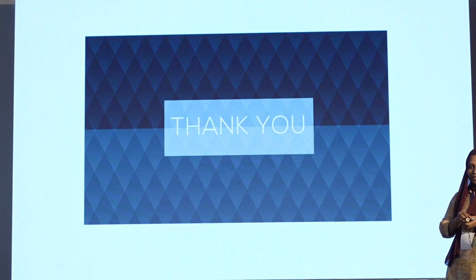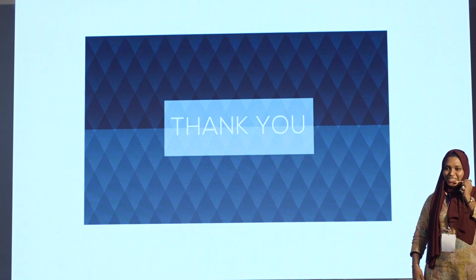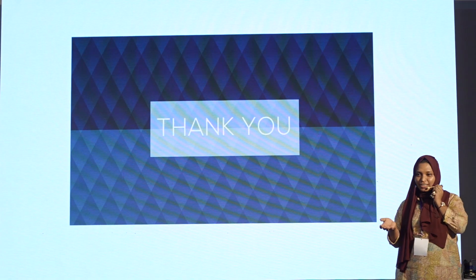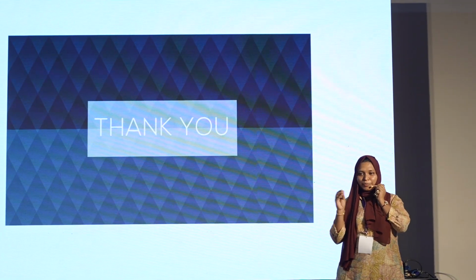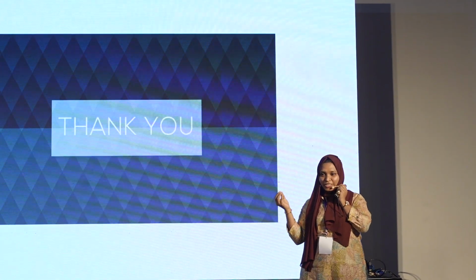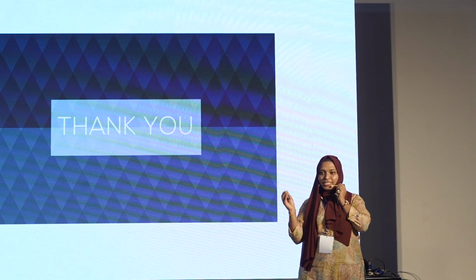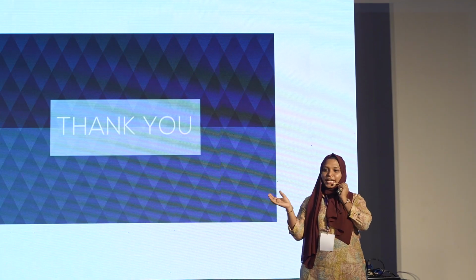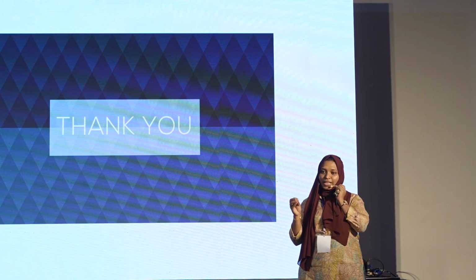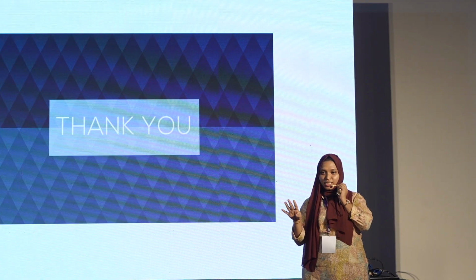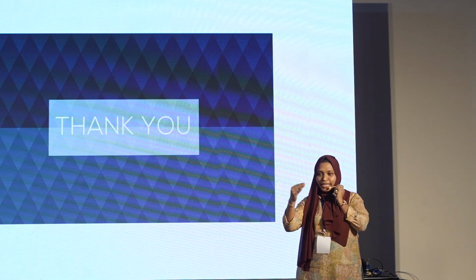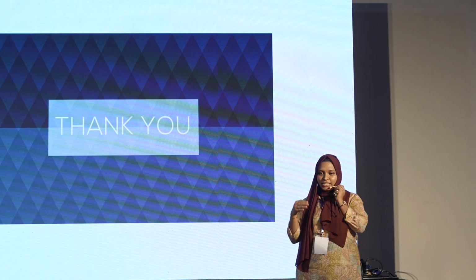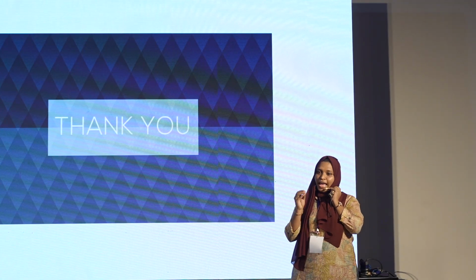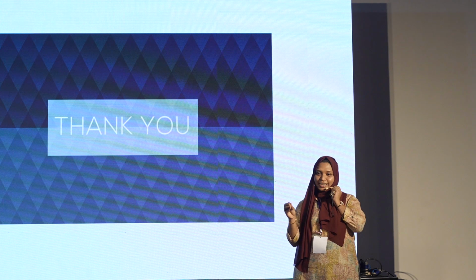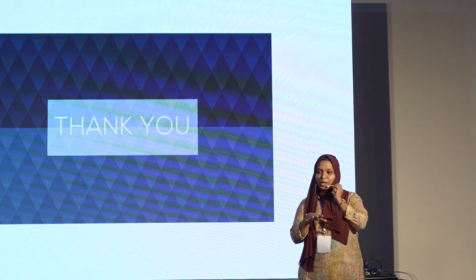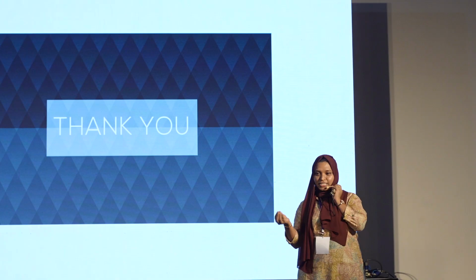Why not selenium? Both tellurium and selenium can be chosen. Our team is now working on selenium as well. But we were impressed by the positive electrode potential of tellurium, that is, it comes around 0.8 electron volt. So we can do polymerization without the aid of any external oxidants or reducing agents. Solely EDOT and Te4+ ions undergo a redox reaction, and this is an in situ process where TNPs would get embedded in the PEDOT matrix. So minimal use of reagents can be done here.